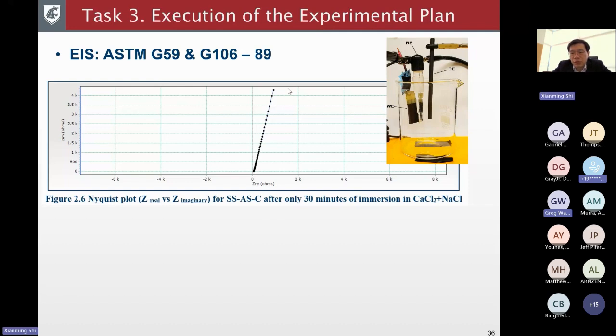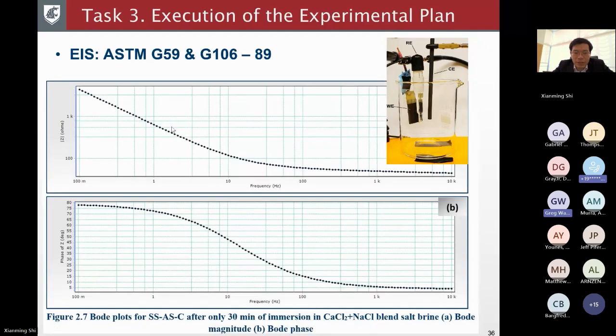Basically, the way it works is you have a metal coupon coated working as a so-called working electrode, or WE, and then you have a reference electrode next to it, and then you have a counter electrode. Between the counter electrode and working electrode, you apply a potential usually, and then you get a current feedback. And these are AC currents or alternating currents. And from the potential to current relationship, you can derive so-called impedance spectroscopy. And there's a lot of details about this method, but I won't go too much into it.